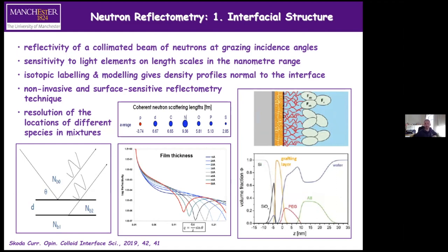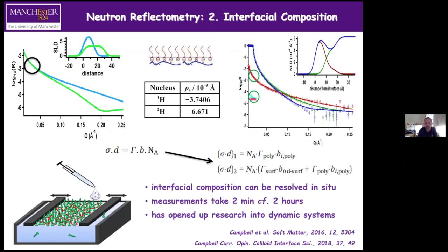Here's another example from the literature of an antibody binding to a PEG layer on a grafting layer on a silicon surface. The data aren't shown, but the result demonstrates the level of detail you can get from neutron experiments. By measuring in different isotopic contrasts, you get volume fractions of all components: the silicon, silicon dioxide layer, grafting layer, PEG brush, antibody, and water — with information about amounts, location, volume fraction, and thickness. That's the normal application of neutron reflectometry.